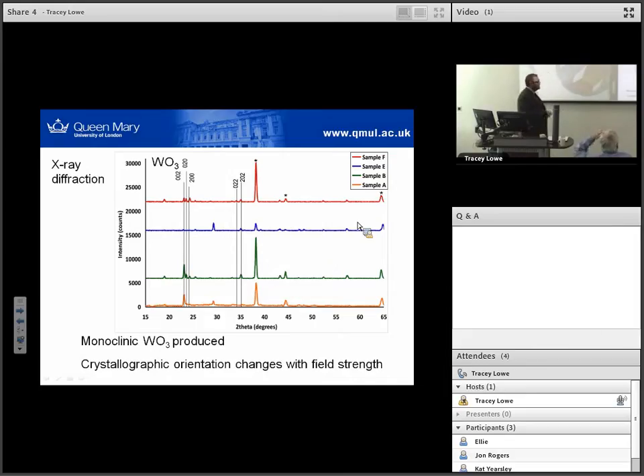We see similar kinds of changes in our tungsten oxide as well. If we consider our film produced without an electric field versus one with a stronger electric field, you get quite different orientation changes with different electric field strength.